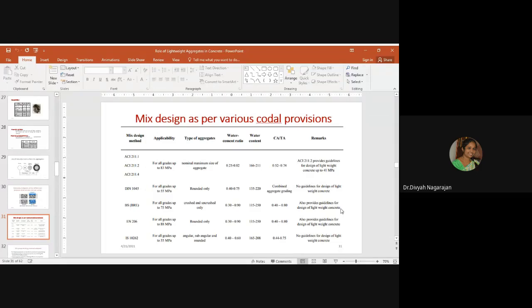Now, the BS code of practice is applicable for all grades up to 75 MPa. Crushed and uncrushed aggregates can be used in this design. A 0.3 to 0.9 water cement ratio can be adopted. The water content ranges between 115 to 250 kilogram per meter cube, whereas the coarse aggregate content to total aggregate content ratio ranges between 0.4 to 0.8. Also, it provides guidelines for design of lightweight concrete.